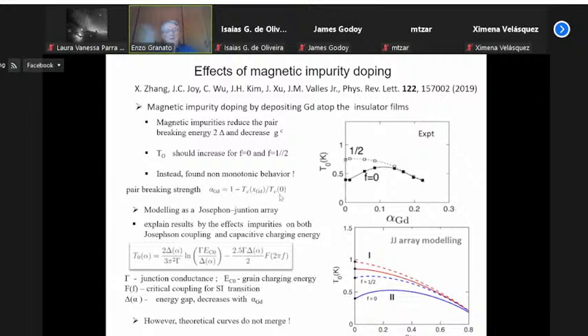To explain the results, they model the system as a Josephson-junction array, and made some approximations. They explain the results by the effect of magnetic impurities on both the Josephson coupling and the capacitive charging energy, due to the fact that the magnetic impurity reduces the pair breaking, and therefore affects both the Josephson coupling and the charging energy. So the activation energy here, which depends on the distance to the transition, has two terms. The first term is essentially the charging energy, but renormalized by the effect of magnetic impurity, minus the Josephson coupling, which is also renormalized by the effect of impurity, times a function which describes the critical coupling for the superconductor-insulator transition.